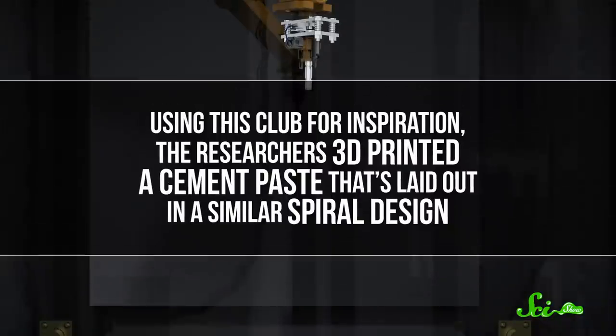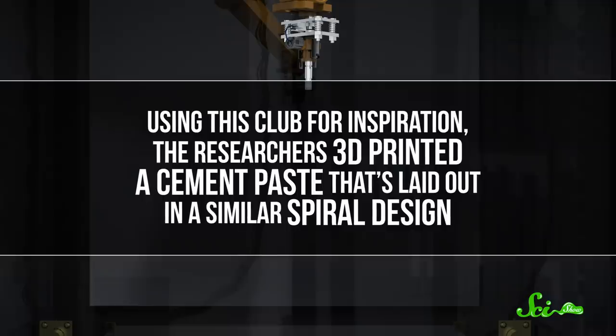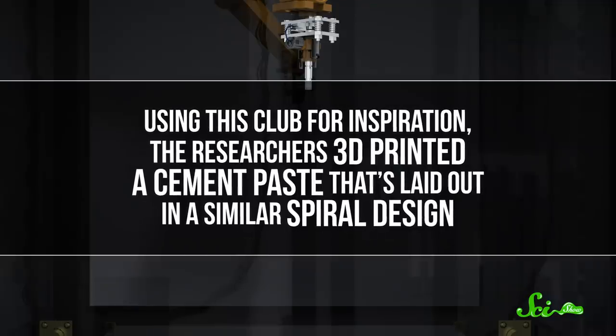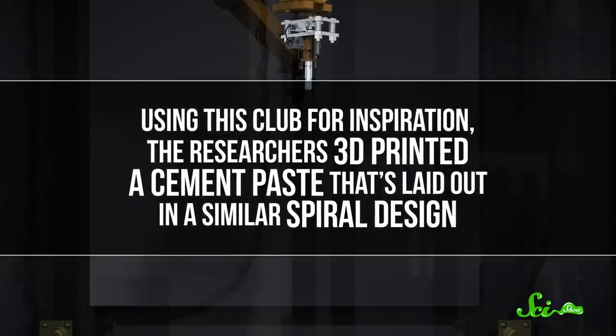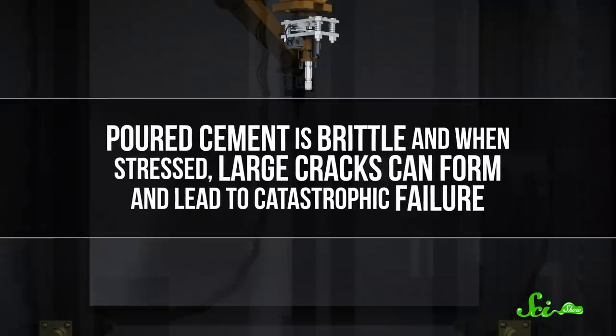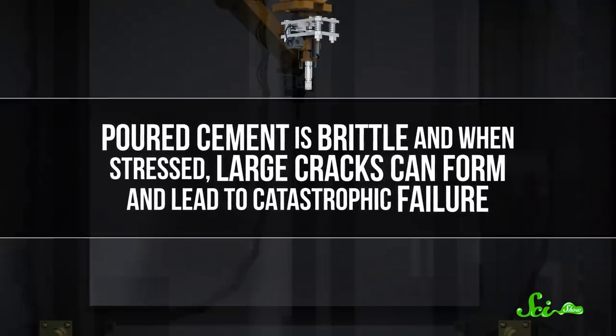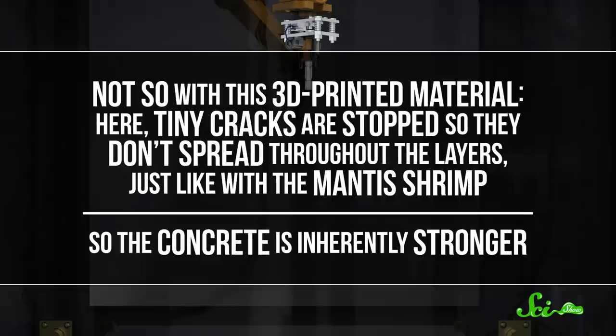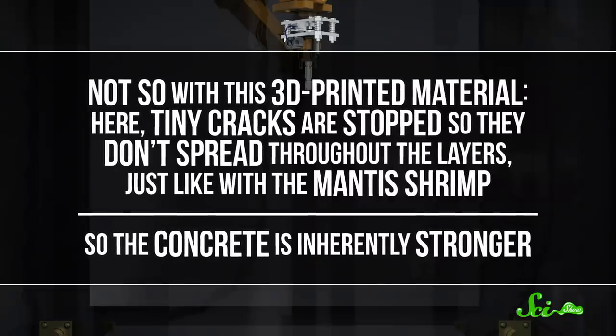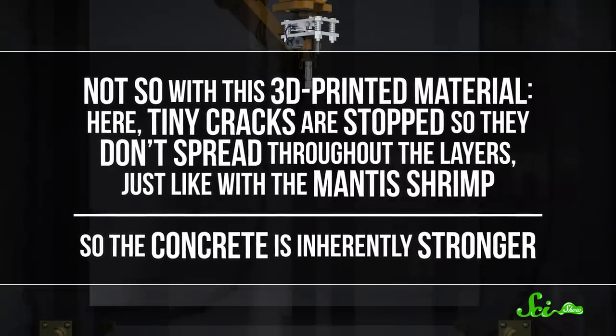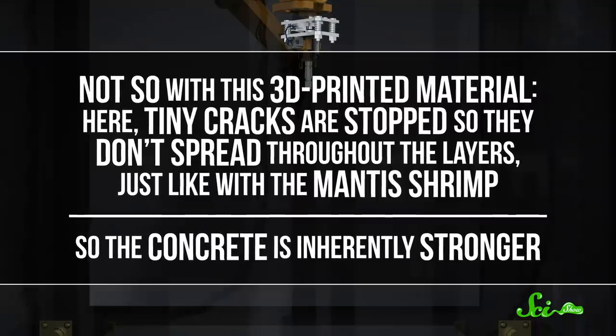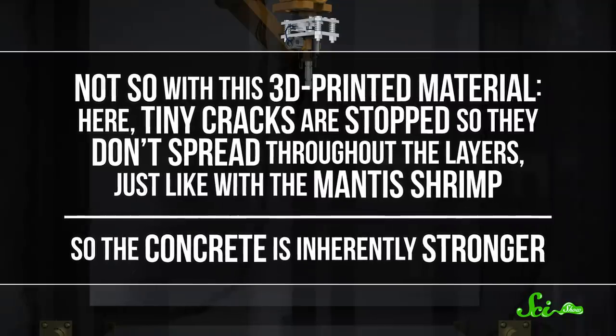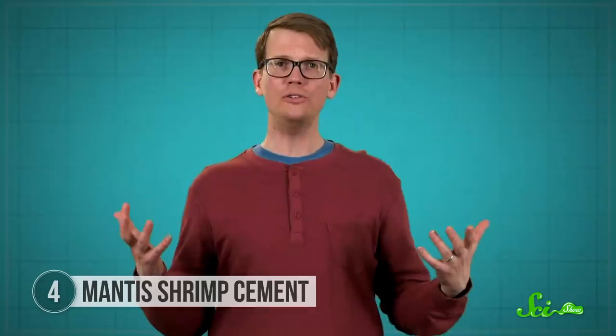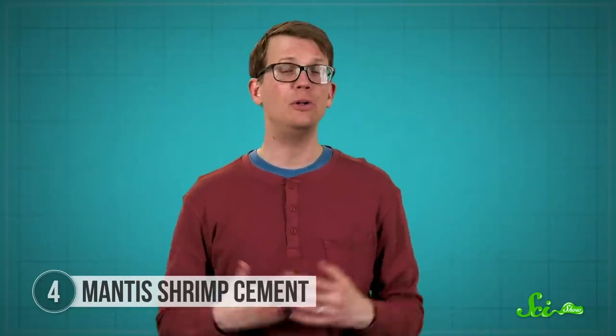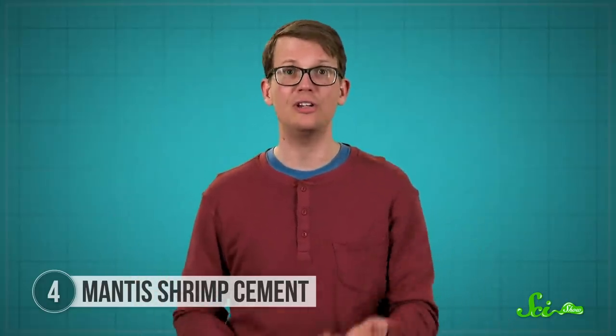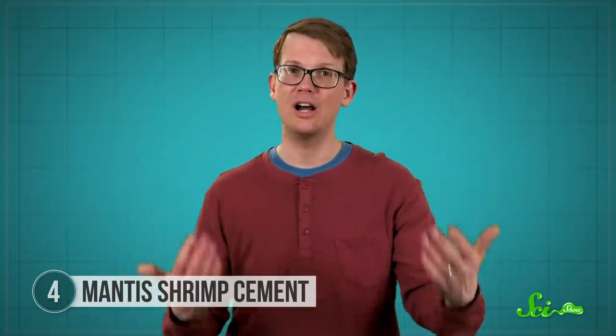Using this club for inspiration, the researchers 3D printed a cement paste that's laid out in a similar spiral design. Poured cement is brittle, and when stressed, large cracks can form and lead to catastrophic failure. Not so with this 3D printed material. Here, tiny cracks are stopped so they don't spread throughout the layers, just like with the mantis shrimp, so the concrete is inherently stronger. The goal is to eventually use this type of material to build more earthquake-resistant structures, and that means less wasted concrete.